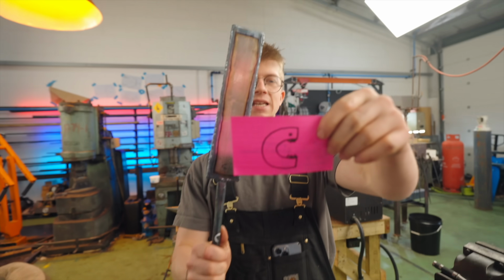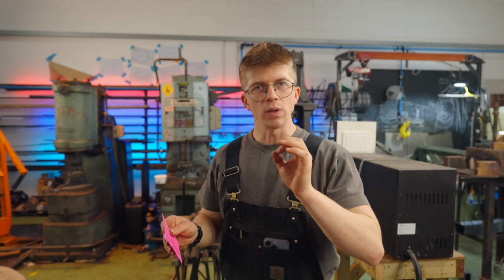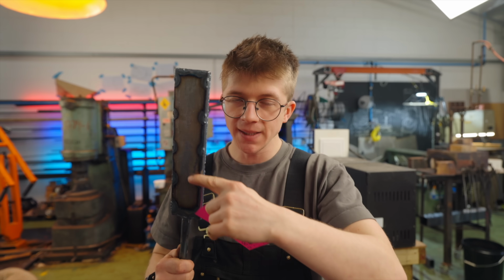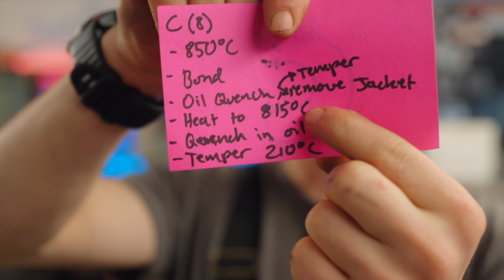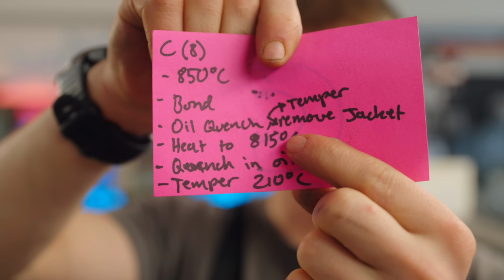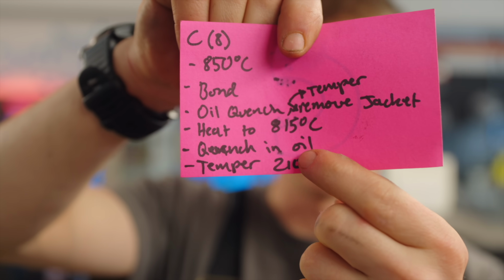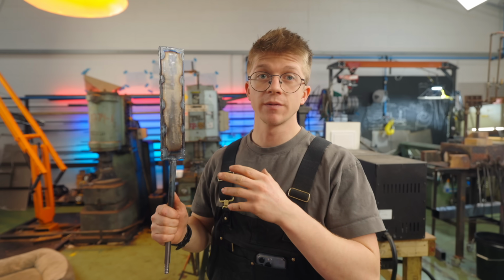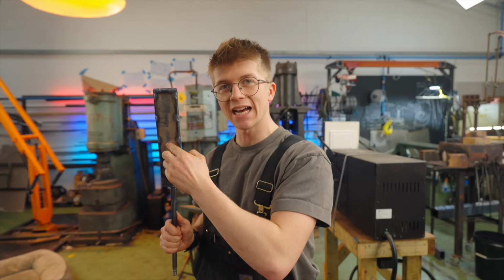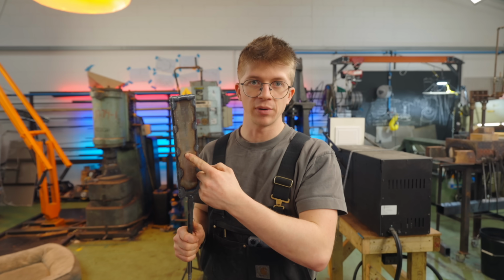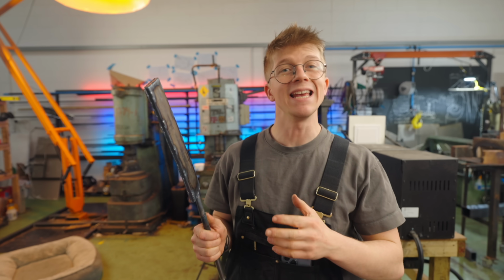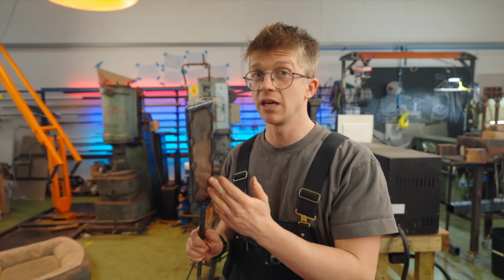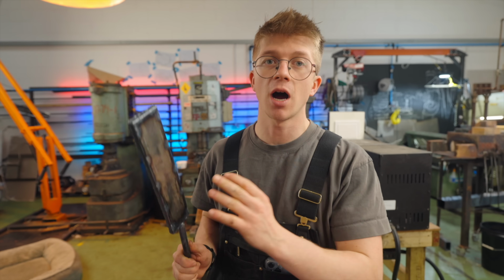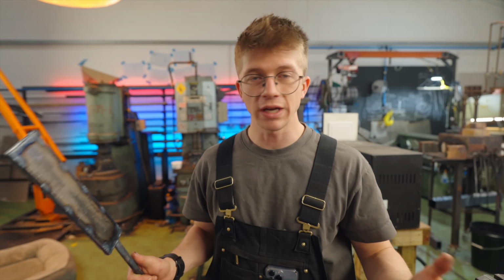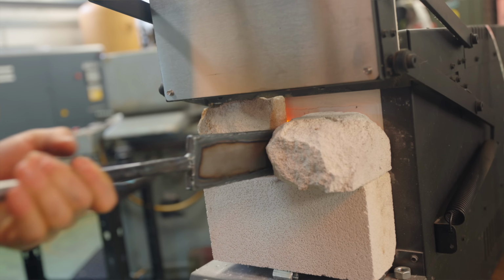And then experiment C. Again, thanks to your suggestions, we heat it, we bond it, we quench it, we temper it like normal. But we then take the mild steel jacket off it, reheat it to 815 degrees Celsius as quick as we can, and then quench it in oil and temper it all over again. And the results of that will tell us how important the jacket was to the lack of hardness of our previous test, but it will also tell us if it's possible to reheat the material back up to that critical temperature after it's been bonded, or will that just form more brittle intermetallic compounds and cause the thing to split apart?